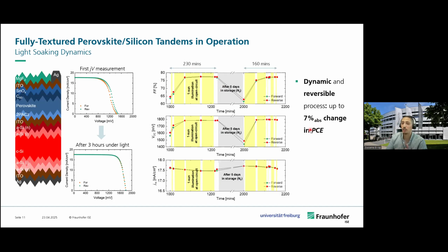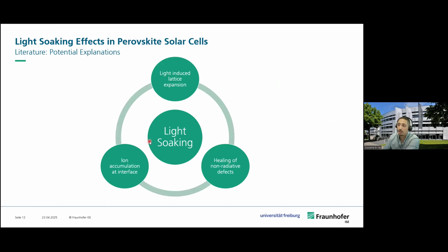Now, this light soaking phenomenon is really bad for multiple reasons. First, dynamic changes have been shown to induce long-term degradation issues in perovskite solar cells, but also having a batch with 20 cells and needing 3 hours to measure every cell is not really pleasing. So in order to understand a bit more where this light soaking phenomenon is coming from, we looked at the literature where light soaking has been demonstrated for perovskite solar cells.